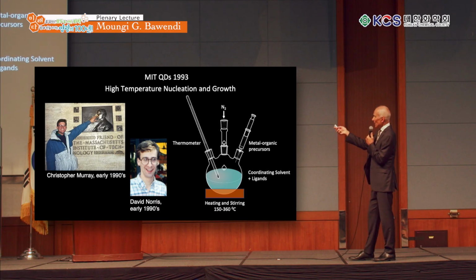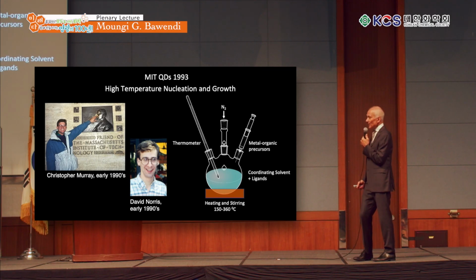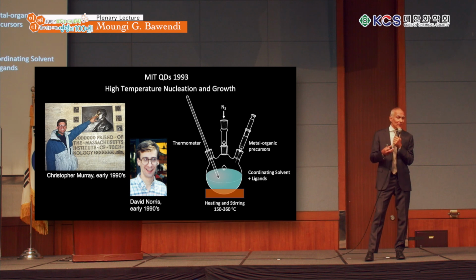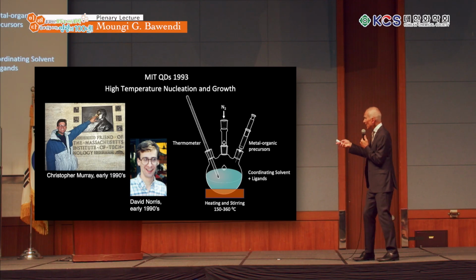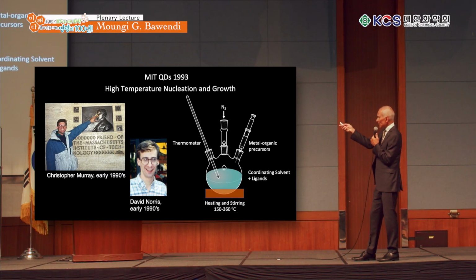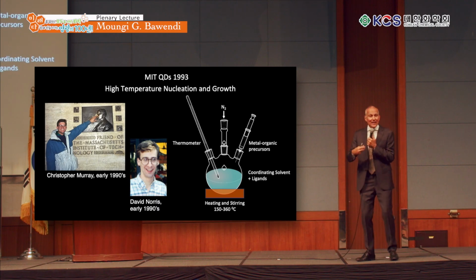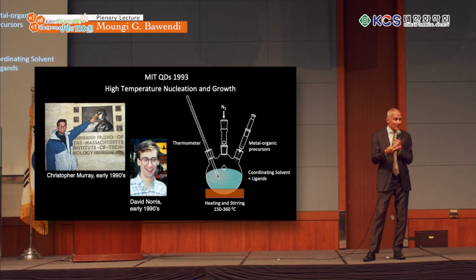And so we had metal organic precursors that were stable at room temperature, quickly injecting them in a high temperature solvent with ligands. The ligands bind to the surface of the particle to slow down its growth and prevent the growth from being catastrophically fast. When the metal organic precursors come into contact with a hot solvent, they break apart and they release the elements that are then made to make the particles. That's the nucleation part. Once you deplete the concentration, then you can no longer nucleate, and you start to grow on top of the seeds that you've created.